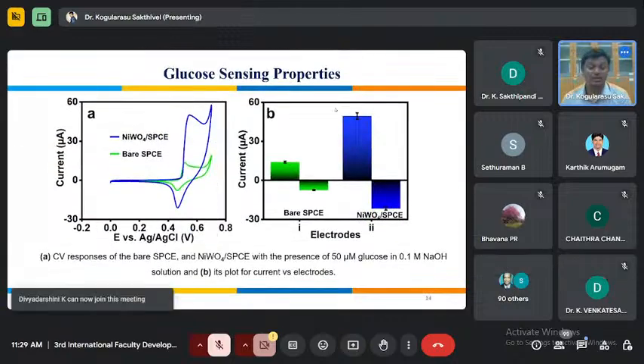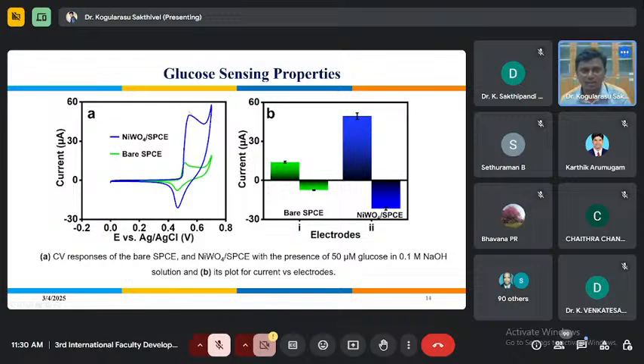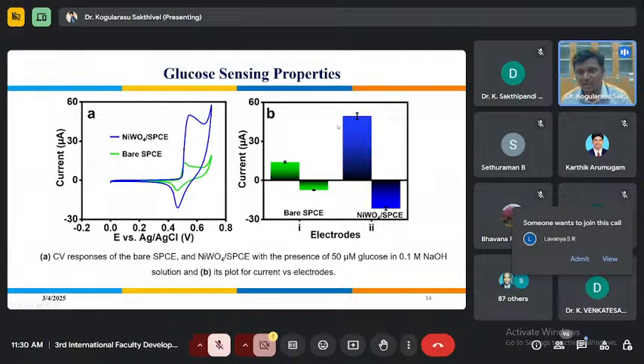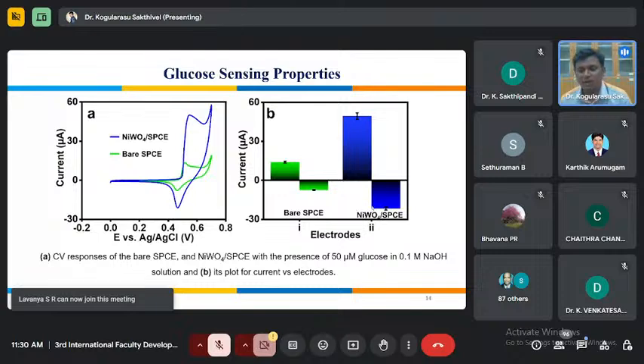And now we are testing it for calibrating it with sensing the real glucose. In figure A, you can see the green one is a bare electrode, without any glucose. This is the result. And when the nickel tungstate is coated and the glucose is tested, of course we can see the higher folds of current. So the green is for the normal bare, which means without the substance, and when it is coated with our nickel tungstate, then it gives a higher peak, which means higher sensitivity. So we have used it, and the reduction and oxidation currents are mentioned graphically for more understanding in B. So here we proved that this material, which is nickel tungstate we have prepared, is capable of sensing glucose.